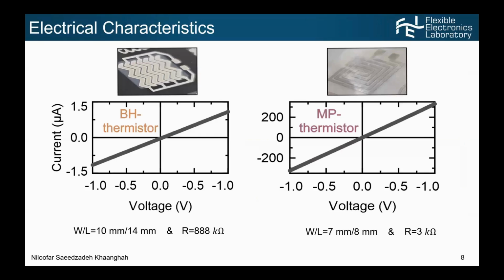So I started characterization by taking a current voltage characteristic first to check the conductivity. As you see, there is a nice ohmic contact and with an average resistance in the order of kilo ohm. And as we use different sensor patterns with different W over L ratio, you see the difference between resistance.